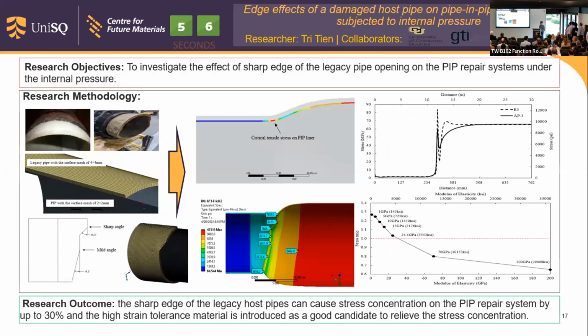I'm researching the edge effect of the host pipe on the PIP under internal pressure. After a long time in service, the host pipe can be corroded and doesn't have the full strength. So the PIP will bear the full load and has high stress concentration at the broken edge of the host pipe. We use finite elements to simulate different scenarios with different materials and loading conditions, and the crack edge as well.